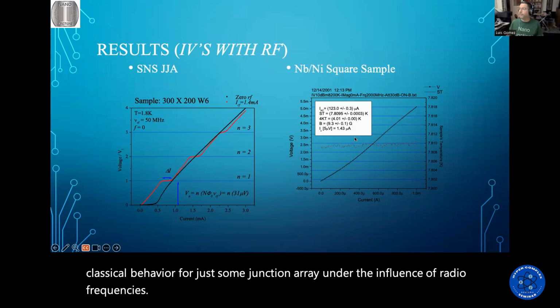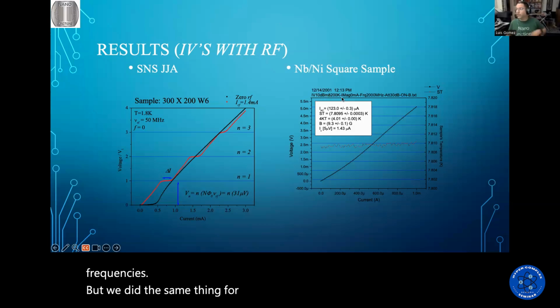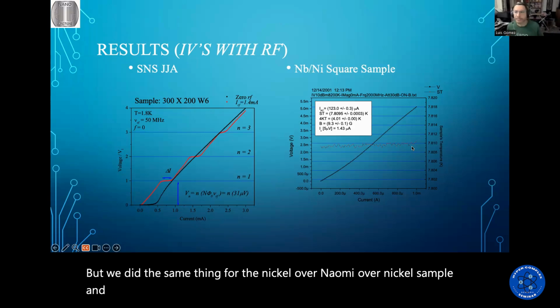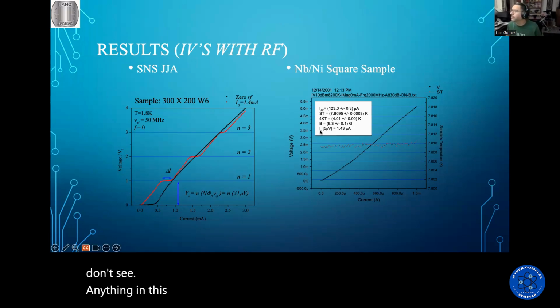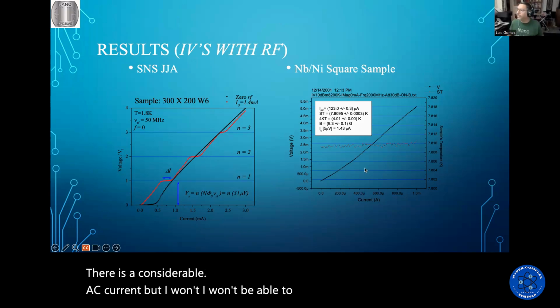But we did the same thing for the nickel over niobium over nickel sample, and I don't see anything in this case. There is a considerable AC current, but I won't be able to see this Shapiro step so easily.